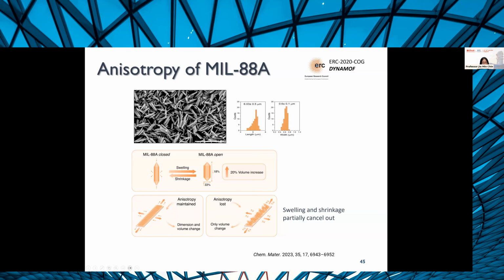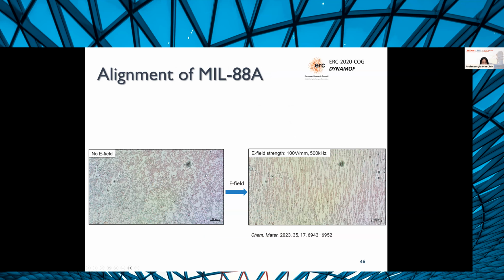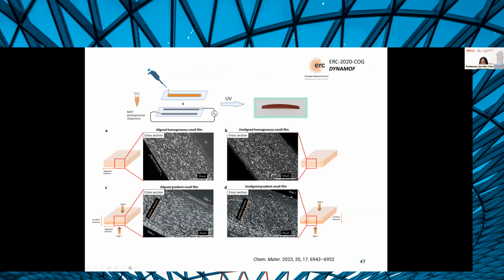And so we synthesize these MOFs and we disperse them in solvent in the presence of an E field. They align very nicely. And we fix them inside different types of polymer matrices, but primarily we worked with PEGDA, polyethylene glycol diacrylate, a photopolymer. In this case, we can either align them using an electric field, and we do that very fast and fix it, so you get quite a homogeneous dispersion, or you can let them sediment a little bit so that you have a gradient in the density of the MOFs towards the bottom. And here you have your unaligned films, where you see the MOFs are randomly oriented.